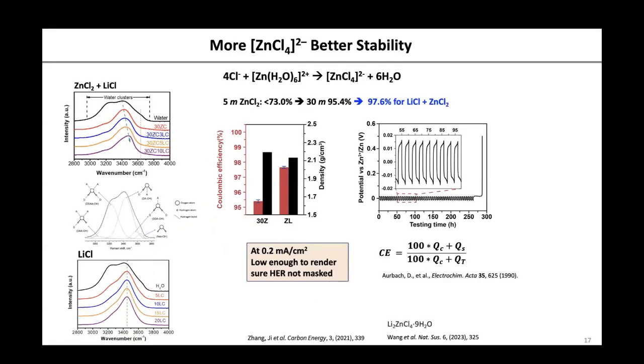All right. So I just mentioned that you have the zinc chloro species here. That's the anions, right? And I mentioned the screening effect. The initial motivation to add lithium chloride to zinc chloride is to generate that screening effect. But beyond the screening effect, we found that we actually generate a different chemical environment for water in the electrolyte. Again, this is the Raman data. This is actually the femtosecond stimulated Raman spectroscopy. Very sensitive. Now, if you add lithium chloride into zinc chloride by increasing the concentration, it's very interesting.